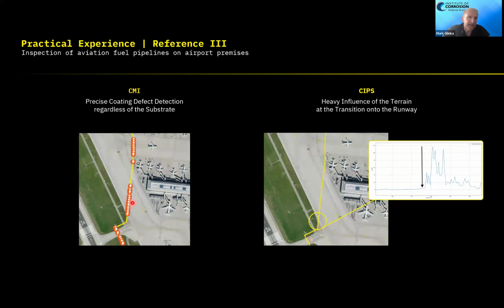You can see all these little lightning icons over here. Those are the coating features. And you can see this is a CIPS measurement. And when we hit the runway, our signal goes bananas because the runway is obviously highly resistive. So I just want to show you that this is possibly also the reason why we work a lot in urban and complex environments, because some data is better than no data. When you cannot ILI the lines and you cannot use any smart pigs or anything like that, you want to have a solution.